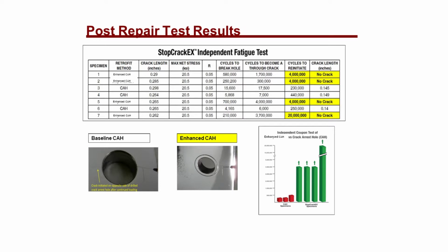The crack arrest holes, the normal way that you do things now, all of them failed pretty rapidly. The best one went to 440,000 cycles, the worst one at 230,000 cycles. The ones treated with the crack arrest, with the bushing, with the stop crack process, all made it to 4 million cycles, and the test was cut off. The spare was run as well just to see how long it could go, and at 20 million cycles, the test was ended. Pretty positive.